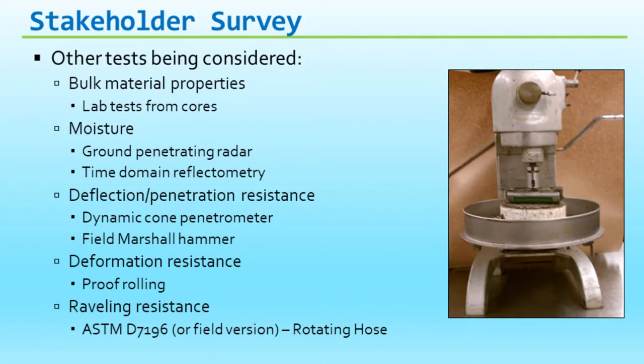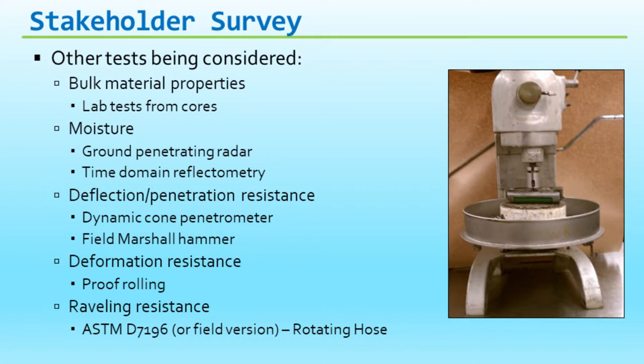From that stakeholder survey, just some of the other tests: some folks looking at bulk material properties, trying to come up with air void contents, some folks using ground penetrating radar for moisture, even some time domain reflectometry, which requires instrumentation of the pavements, but there was some evidence of that. Dynamic cone penetrometer, a couple of people have played around with that, Utah, in addition to the work that Utah had done. Proof rolling is quite a big concept, but no real guidance on it. Some guys using a 5,000-gallon tank, some guys using a 10,000-gallon tank. Weren't sure if the tank was full, whether it was empty, half full.